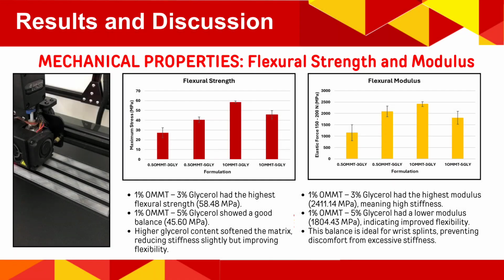For flexural properties, 1 weight% OMMT and 3 weight% glycerol exhibited the highest flexural strength at 58.48 megapascals, demonstrating excellent resistance to bending forces. However, its high modulus of 2411.14 megapascals suggests that it may be too rigid for comfort.